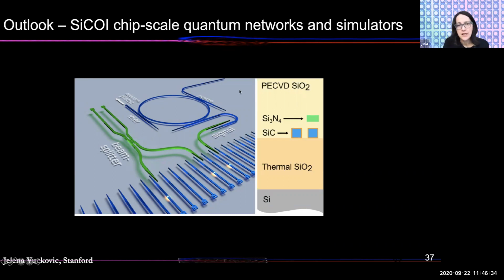We can also do directly quantum frequency conversion in silicon carbide. I think that's clear now from the experiments that I've shown. So you don't really need lithium niobate or any other nonlinear crystals. You can do frequency conversion directly on the same platform that hosts your quantum emitters. Because for quantum networks, you certainly want to generate the output photons that are at the telecommunication wavelength range so that you can transmit them over longer distances. So quantum frequency conversion from 800 or 900 nanometers to 1.5 micron could be done directly in silicon carbide.